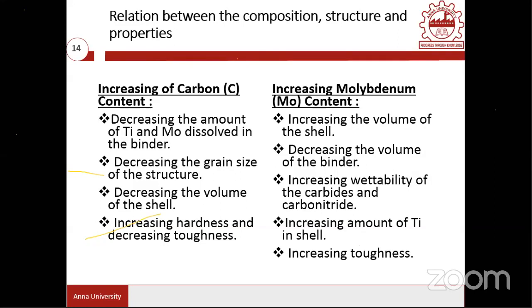The alloying element will sometimes be a metallic element present in the compound or in the starting material. So what is the role of this material? Carbon content is going to decrease the amount of titanium and molybdenum dissolved in the binder. And one important property that carbon is going to increase: the more carbon percentage in the TiCN, or probably in the TiC or WC addition, that is going to increase the hardness and decrease the toughness. So this point has to be remembered.